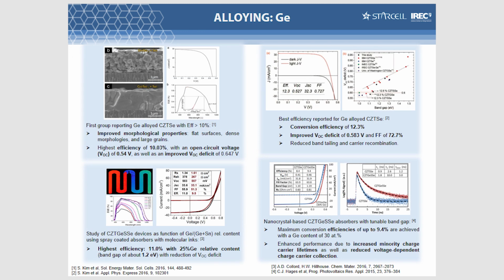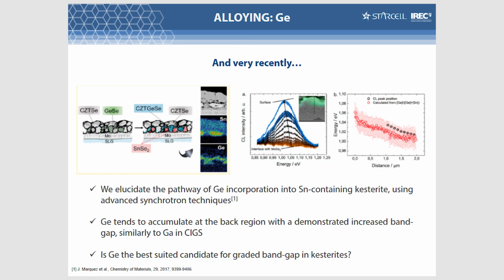Nevertheless, with germanium, there are several works using germanium for alloying kesterite, and all of them have demonstrated a very positive effect. Germanium is easier to work with than tin, so you can easily tune the band gap using germanium. You can get very nice charge transport properties and very good efficiencies as well with germanium, quite easily.